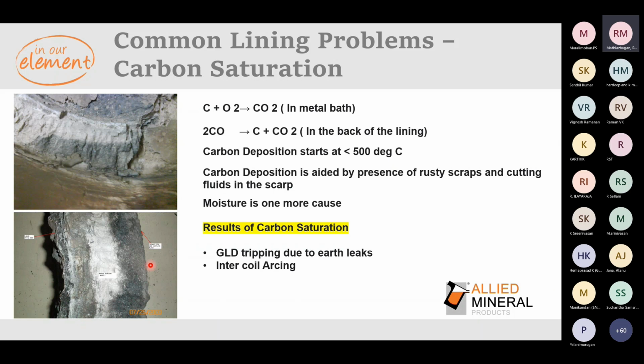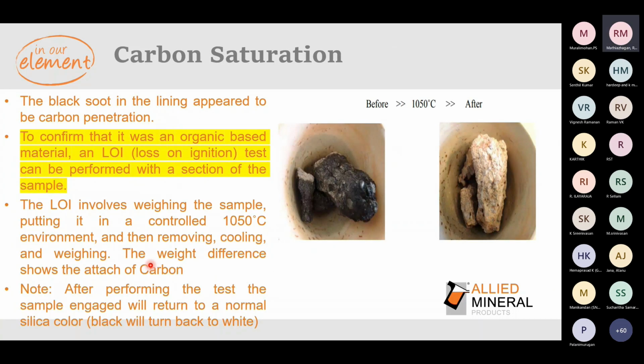What happens when carbon saturation happens? As it grows and grows, GLD tripping happens due to earth leaks, and intercoil arcing happens. In case you come across this in your foundry, to understand whether it's carbon or not, you can easily test it in your lab by doing an LOI test, that is, loss on ignition test. Take this black refractory, put it in your furnace, and take the temperature above 1050 degrees Celsius. The weight difference between the initial charge and the final after heating to 1050 indicates the carbon content. Also, the silica turns white again. All the carbon evaporates, and the refractory looks white again. If you see this picture, that indicates the same. So that's an easy check which can be done even by you in your own labs.